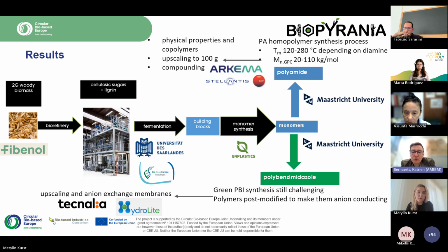For the polybenzimidazoles, synthesis of polybenzimidazole in a green way is still very challenging. But we made some polybenzimidazoles from our monomer, and we also post-modified them because you have to introduce charged groups to make those polymers anion conducting, because we want to use them as anion exchange membranes in electrolyzers and fuel cells. And samples were transferred to Tecnalia for testing and processing into membranes.